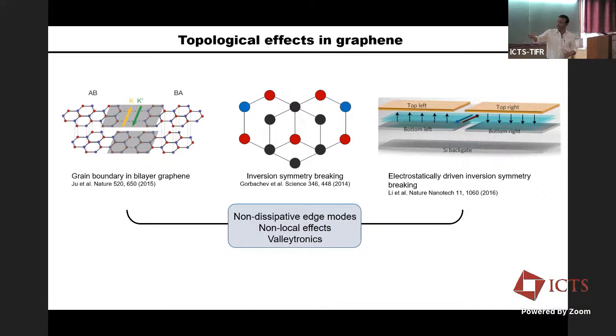You can see that if the bilayer stacking order, which is AB to BA, where which carbon atom is sitting on which layer, if that can be reversed, it can lead to topological states along the grain boundary and non-dissipative transport. Many people have looked at various aspects of it.